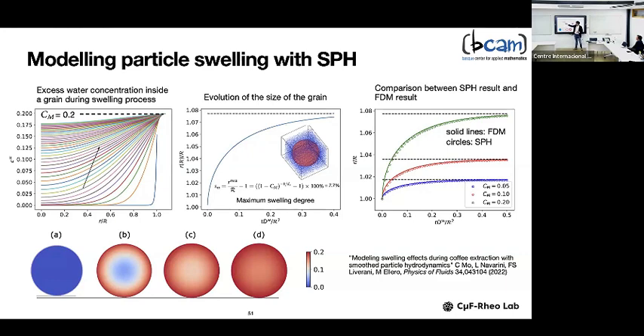the swelling equation. For example, if we take Cm equal to 0.2, we have a maximum swelling ratio of 7%, which is really, really small. If you see 7%, it's really the difference between this particle and this particle. You can see there's almost no difference, but these are the kind of swelling reported in coffee particles by experimentalists. They are between 3% and up to 10%, not more than this. This is not a huge effect. We will see that already this effect, when you talk about a really packed bed of coffee particles, will produce some alteration in the permeability.